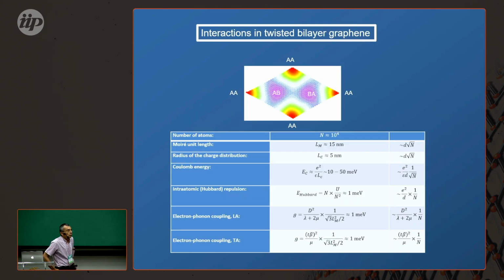But let's go now to moires. As you are already very much aware, moires are characterized by a large, very large unit cell, which contains about 10,000 atoms, and the lattice unit is about 15 nanometers. That gives a natural dimensionless parameter which allows us to classify the interactions, which is precisely how big the moire unit cell is, how many atoms you can fit inside it, about 10,000.